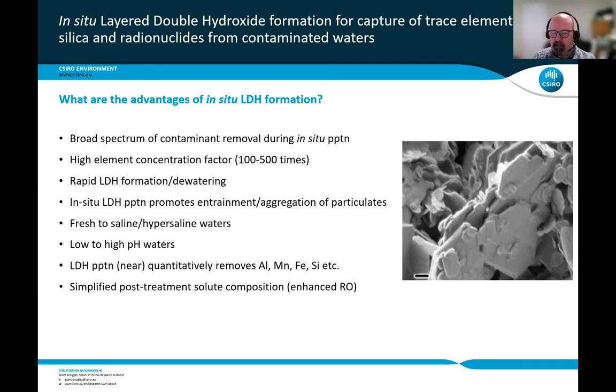You get very rapid formation. Once the conditions are right, the formation is instantaneous, and you also get extremely good settling, and I'll talk about that in a moment as well. Another really good fortuitous characteristic is it promotes entrainment/aggregation of particulate materials. Once you form these LDH instantaneously, they'll form bridges between colloids and particulates. And so you can actually clarify turbid waters.